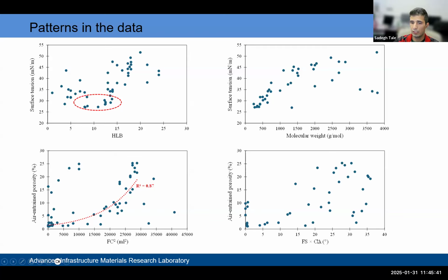Another interesting observation is that our stability factors, which are the foaming stability and contact angle, also correlated pretty well with the air entraining performance.